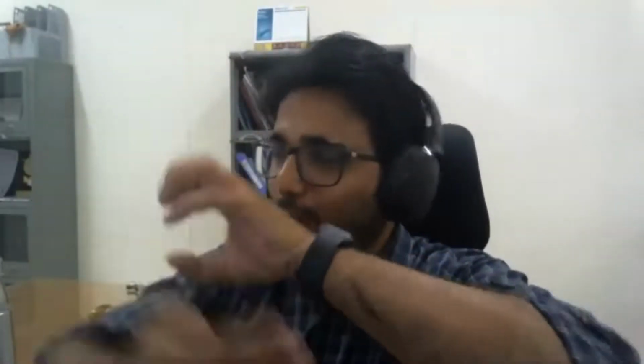What I mean is the recycled aggregate mortar content. So this is the aggregate. If it is surrounded from the four sides with the mortar, then, as highlighted by Rohit, the interfacial transition zone will be poor from all the directions, and it will be easy for the crack to propagate. But on the other hand, if you have a mortar content sticking here only, let's say 60% mortar content, and we are loading it here, the crack is coming from here, so it will take some time for cracks to propagate from this ITZ. So in that case your strength will be higher, so it's really difficult to relate it.